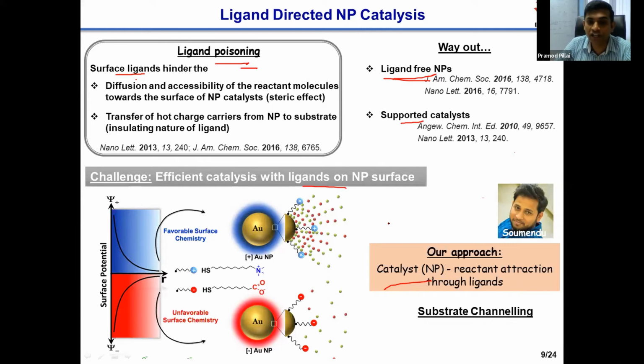So here what we are doing is attracting the substrates to the surface of the nanoparticles, so that the distance between the nanoparticle and the reactants can be reduced, and in that process you will increase the local concentration of the reactants around the catalyst, and this can have a positive impact on the catalysis. So our idea is on substrate channeling. We are interested in channeling the substrates towards the catalyst by playing around with some non-covalent interaction.